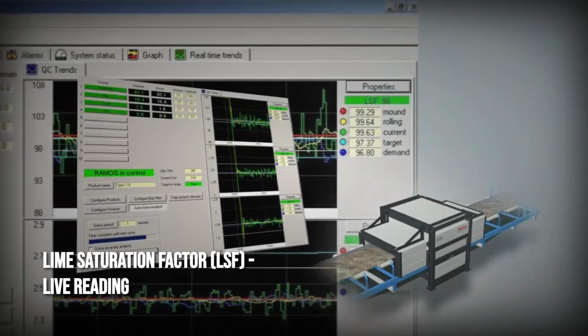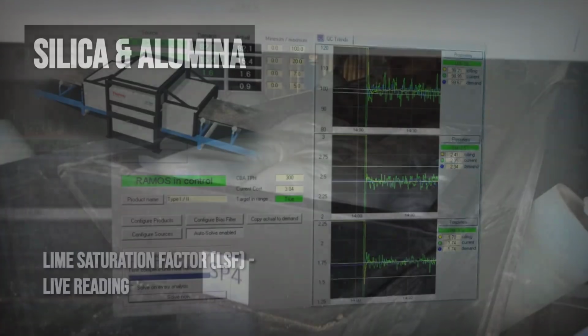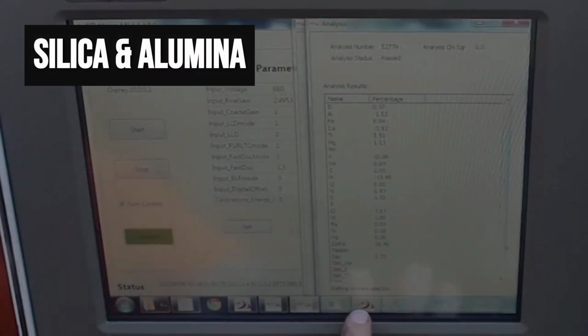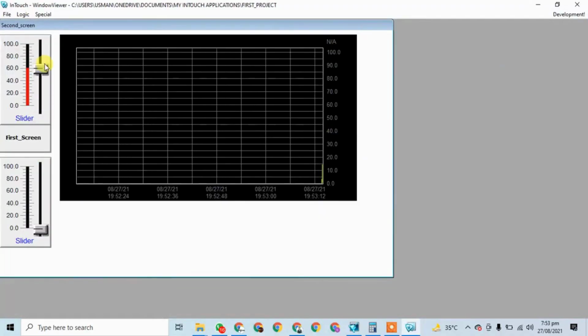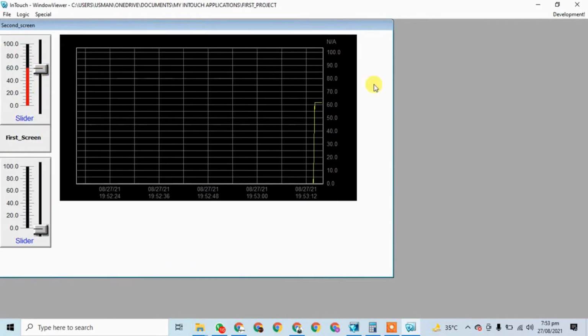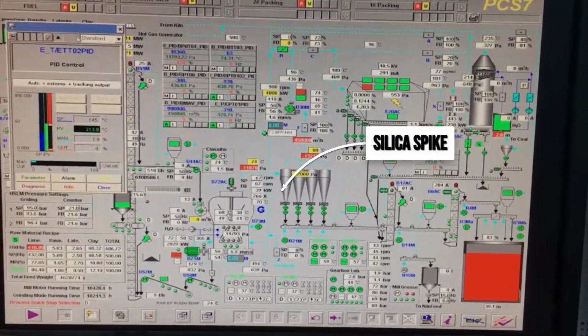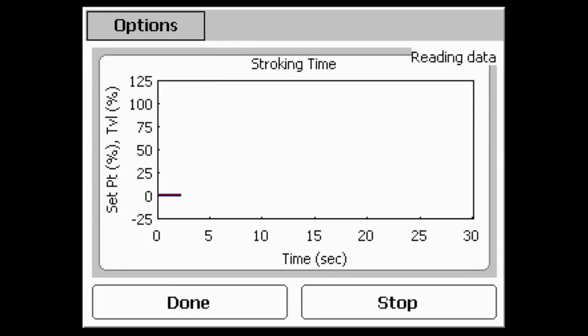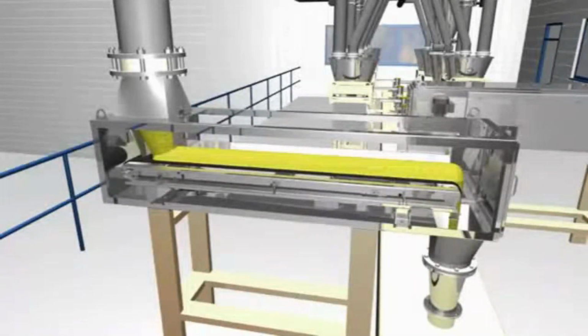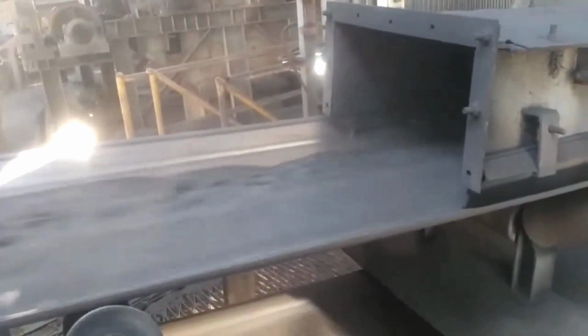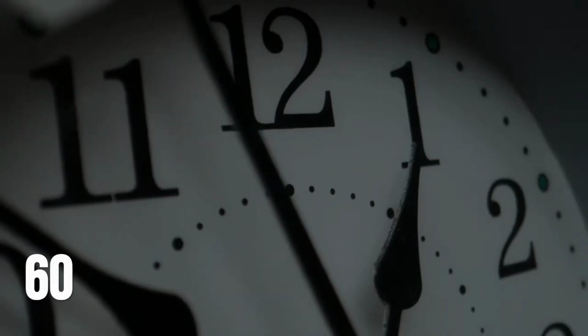The lime saturation factor, known as LSF, the silica modulus, and the alumina modulus appear as live trends, their lines rippling across the screen. A sudden spike in silica or a dip in alumina sets off a cascade of algorithmic adjustments. Proportioning valves shift, corrective fines are dosed, and the flow of raw materials is steered back on course, all within the next minute's cycle.